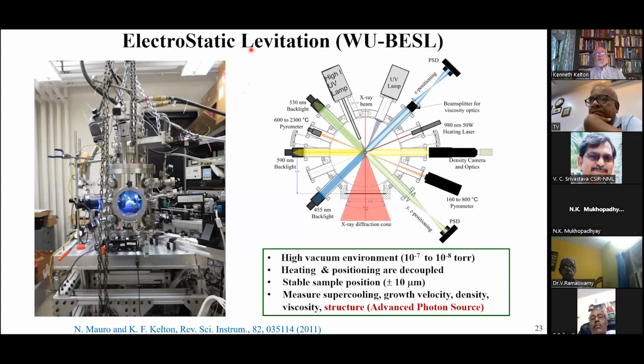We make our measurements in something called an electrostatic levitator. And here's the one that sits in our lab. You can see the blue in here. That's not just for photogenic reasons. The way this works is we have two sets of vertical electrodes with about 10,000 volts applied to that. We have two sets of orthogonal side electrodes with a smaller voltage, about 3,000 volts, applied to that. All of those voltages we can control with a computer.